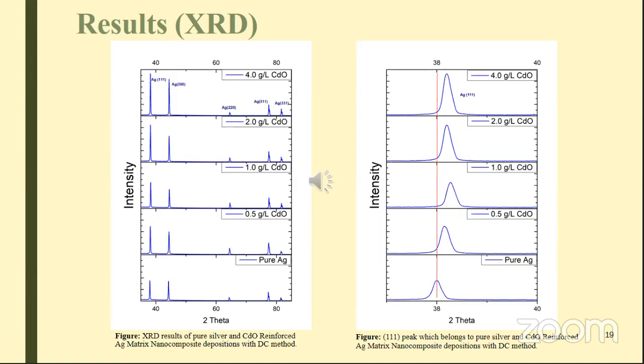The intensities of peaks have changed due to composition. The cadmium oxide reinforcement caused an increase in the 111 peak intensity when pure silver and cadmium oxide silver coatings are compared. Also, cadmium oxide reinforcement caused a significant increase in the silver 200 peak.